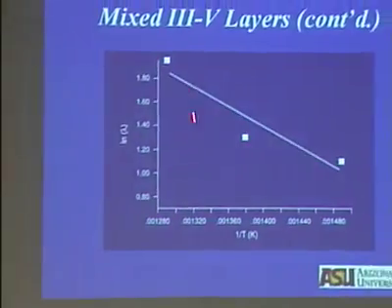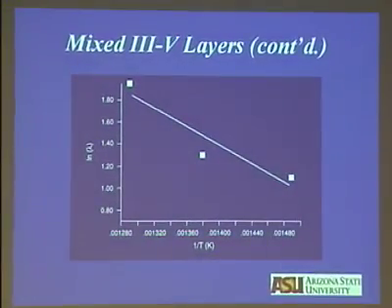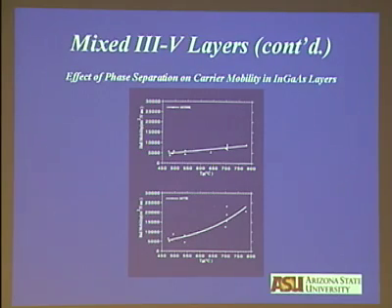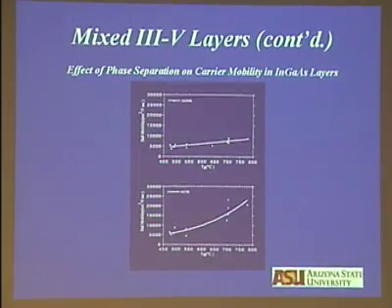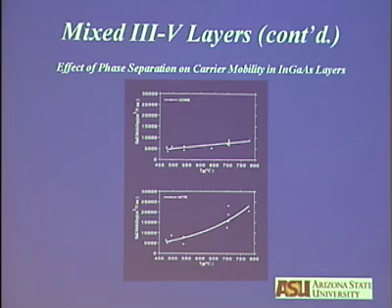not bad. What it is telling you is that we can measure the activation energy from it, which is 0.25 eV, and that correlates with the migration of arsenic on the surface of these layers. So we can correlate that. Now, does phase separation have an effect on properties? The interesting question is, you can keep studying physical metallurgy, you can study semiconductors, but does it have an effect on properties?